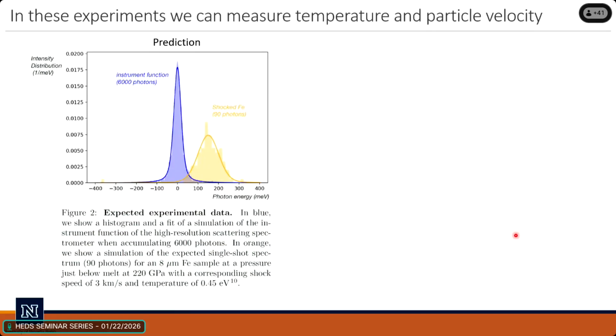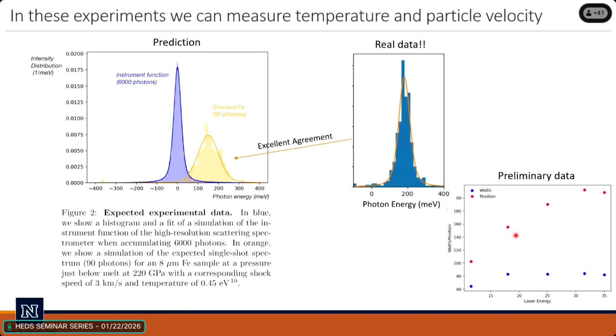And so here's the prediction, right? Here's the cold, and then here's the broadened shifted spectrum. And in the experiment, we measured this broadened shifted spectrum pretty well. So we were able to measure the particle velocity and the temperature behind the shock. We are having some trouble matching this up with the VISAR right now, and we're talking to some people here to try and figure that out. But with the thicker shock targets, you have much more freedom in terms of material choice.